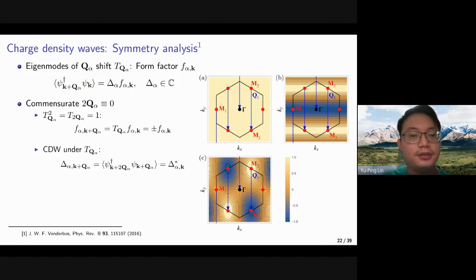And the second thing to do is to look at the charge density wave order under TQ. So we notice that at K plus Q, the psi dagger psi is actually equal to, because 2Q is equal to 0, just psi K dagger psi K plus Q. And it is the complex conjugate of the order at K. So combining these two, we could conclude that the complex amplitude should be either plus or minus itself when we apply a complex conjugate. That is, it should be purely real or imaginary.